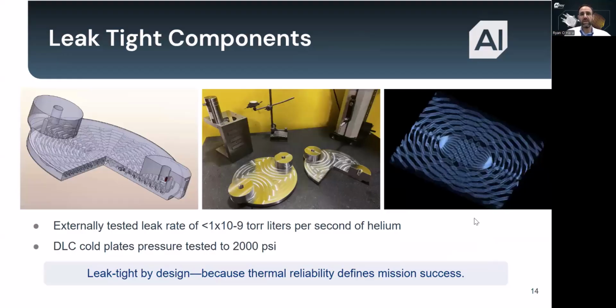So one of the questions we get with advanced cooling hardware is reliability. Can it handle pressure? Can it remain leak tight in the most demanding environments? And the answer is yes, and this slide shows the proof. On the left is a cold plate we manufacture for semiconductor fabrication equipment. Uptime is critical and leak-free operation is mandatory. The part was externally tested for helium leak rate and demonstrated less than 10 to the minus 9 torr liters per second. It's effectively leak-free, exceeding the standards required in the semiconductor industry.